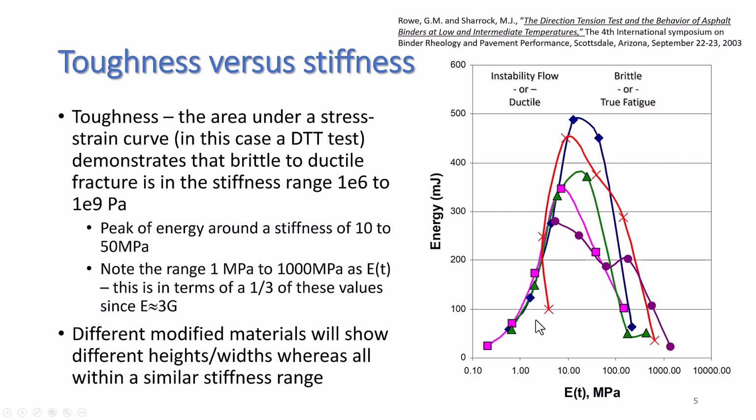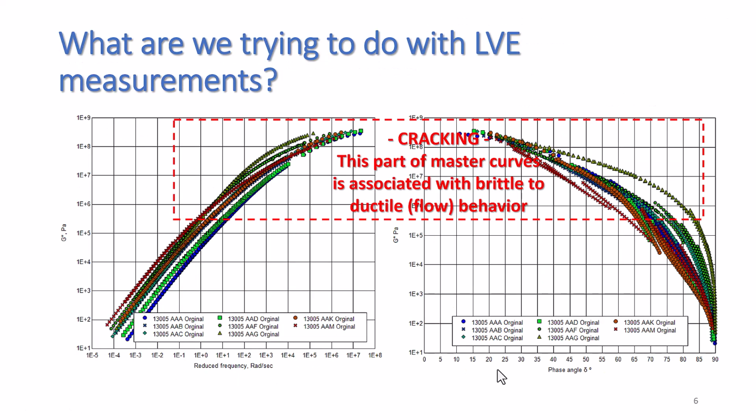Something's occurring in that region. We don't have anything very much going on lower than a megapascal in terms of the stiffness. So now if we look at this graph again, this is the same graph that I showed earlier. What we can do is say, well, this is a megapascal here. That other data was an E of t, so I've just drawn my line a little bit lower to reflect that a G of t is really E of t divided by 3.